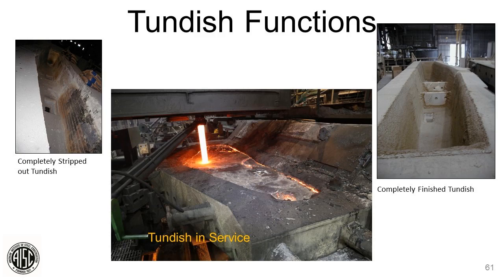The Tundish is kind of delta shaped. The picture on the left-hand side shows what we call the running line, the wear liner. It is consumable, so we'll take it back to a safety lining. That's what you're seeing right there. It's a torn out Tundish. On the right-hand side, upper right-hand corner, you'll see a Tundish that's sprayed and ready to go back into service.